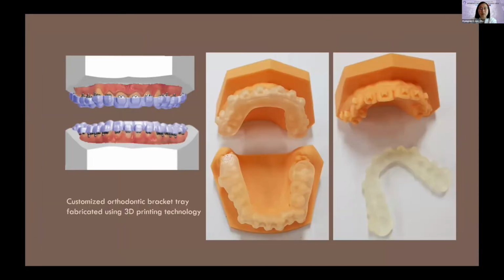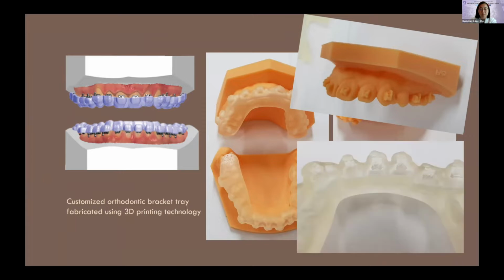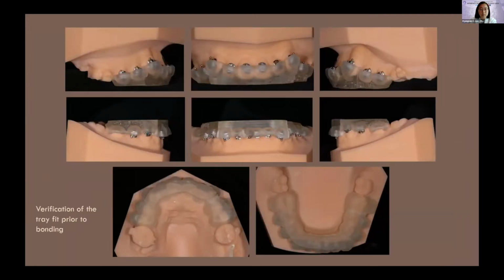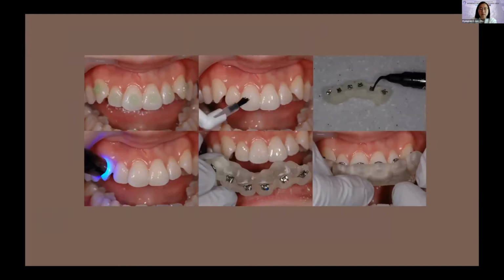A bonding tray was designed. The customized bracket tray was printed using a 3D printer. We sent the file with the finalized bracket position to the company, and the tray with the brackets was delivered a week later. Once the trays were fabricated and delivered, the fit of the tray was checked prior to bonding. After tooth preparation with etching and primer bonding, light-polymerized resin was applied to the enamel surface and bracket bases.